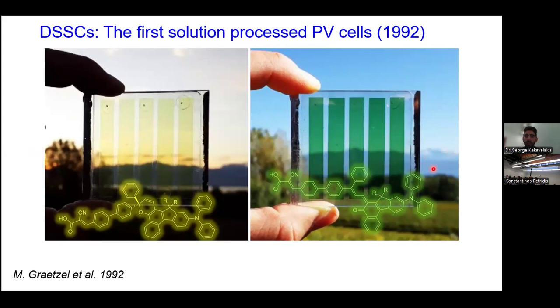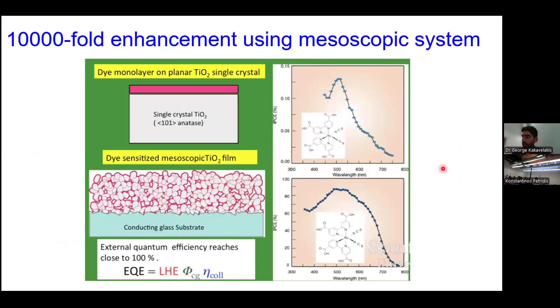Okay, very nice demonstration. And what was very surprising at this point was that if you had a flat area of titanium dioxide, the efficiency was very poor because the dye was only adsorbed on one surface. But if you made this titanium dioxide as a mesoporous layer, you were able to increase the surface area, the dye was adsorbed in a much higher volume, and the quantum efficiency, which is the number of photons converted to electrons, went up from 0.1% to close to 90%, which is comparable to what a silicon solar cell can do.